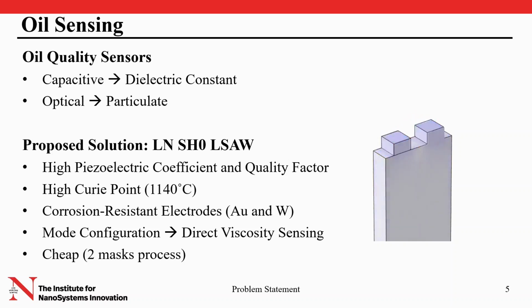In this case, we're employing corrosion resistant electrodes such as gold and tungsten. And this works because of the unique way that the mode shape is configured. In particular, we see that the whole of the displacement is in the electrodes, which means that their motion will be impacted by changes in viscosity of the surrounding fluid. Moreover, this resonator is very cheap to fabricate, as it only constitutes of 2 masks.